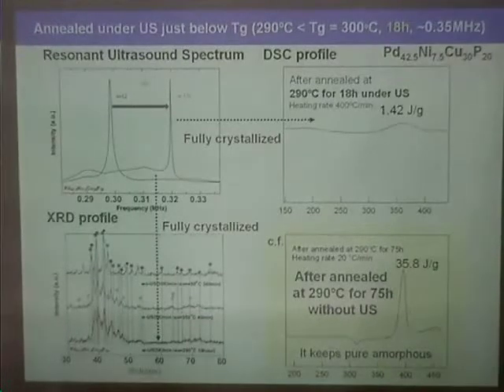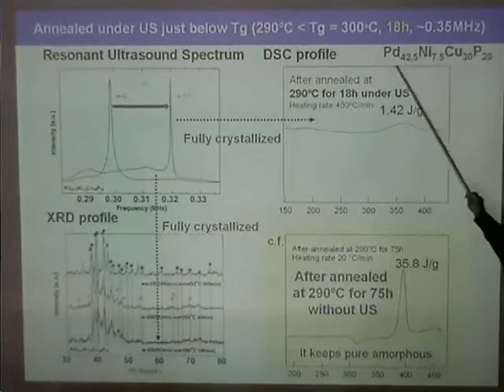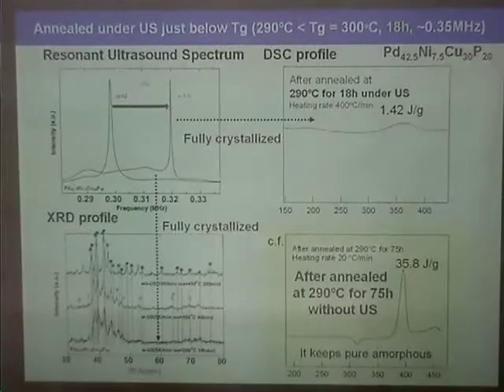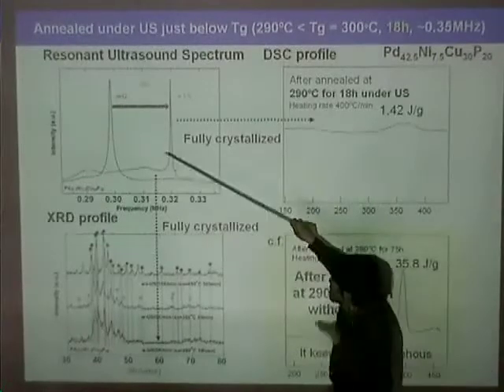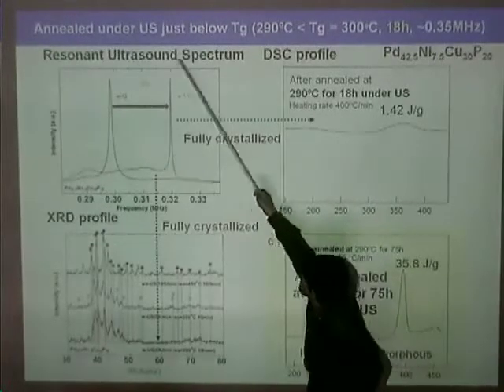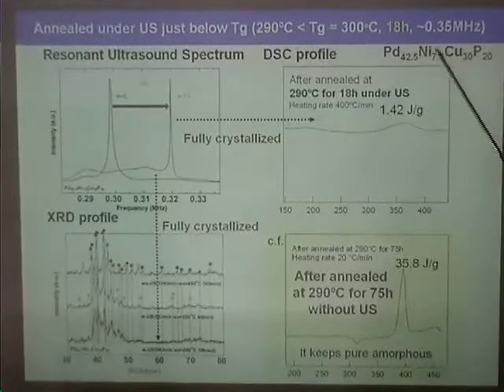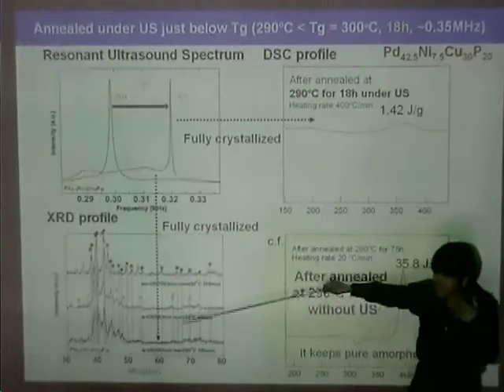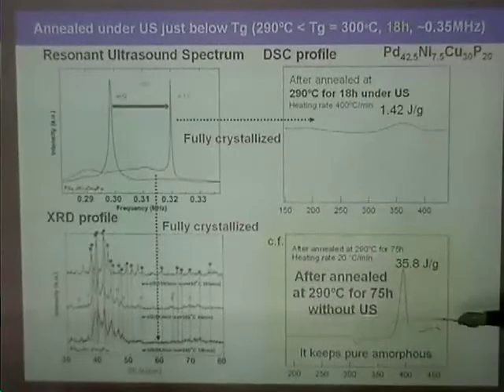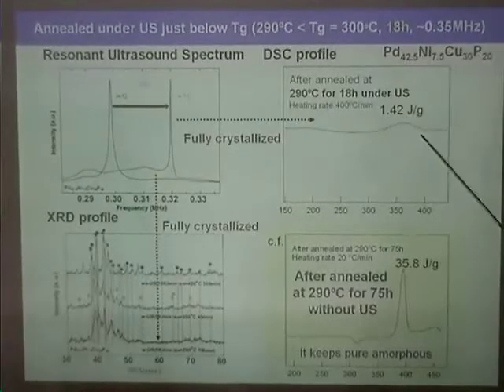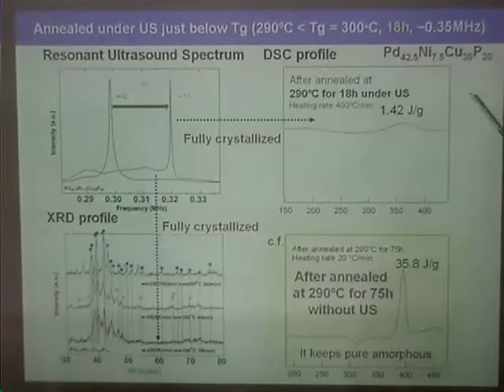So this is a result obtained for the palladium-nickel-copper-phosphorus metallic glass. This is the most stable metallic glass in the world. When we annealed this sample just below the glass transition temperature for 18 hours under the ultrasonic vibration, we found that the crystallization occurs like this figure. After that, the DSC signal indicated no crystallization heat. Therefore, the sample was fully crystallized.